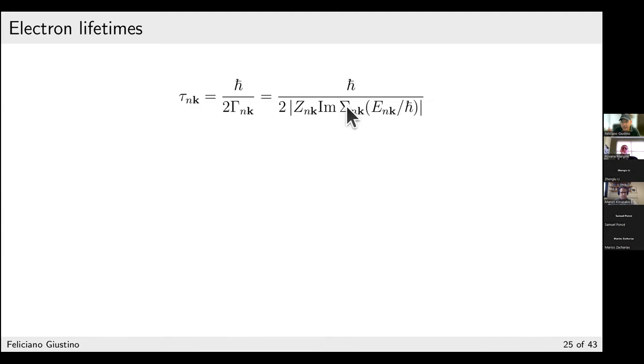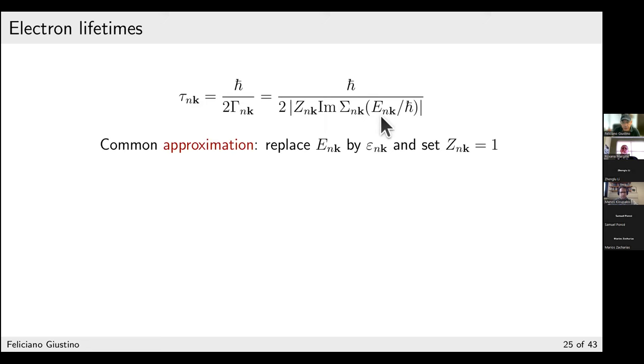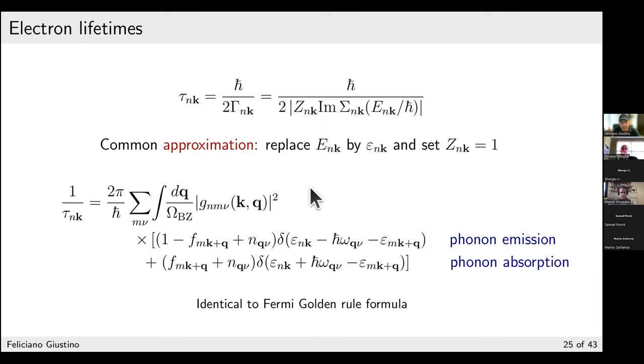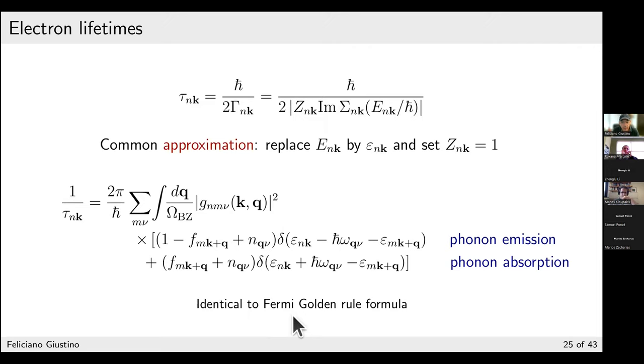The electron lifetime is the reciprocal of the imaginary part of the self-energy. Expressed in terms of Kohn-Sham states and matrix elements, the lifetime involves an integral of the electron-phonon matrix element squared times occupation factors and delta functions enforcing energy conservation when an electron emits or absorbs a phonon. This expression is identical to what you obtain from Fermi's golden rule in semi-classical models of electron dynamics in solids — under suitable approximations, many-body approaches recover the same physics as simpler empirical approaches. This is the key expression for calculating scattering rates for transport.